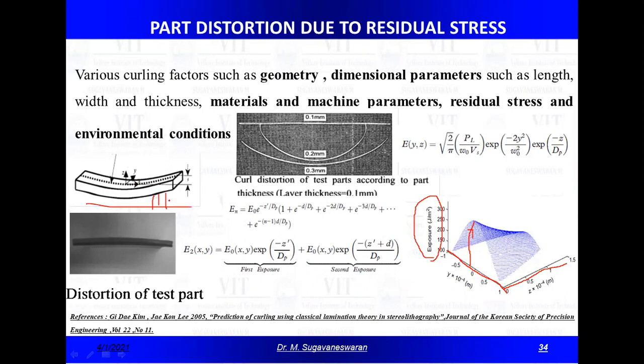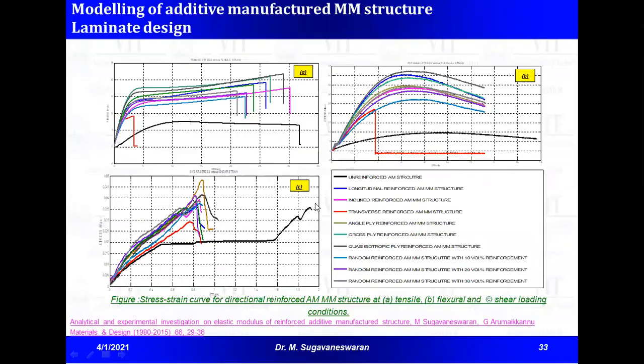But once we remove the support, especially in plastic material, that too in thin features, it automatically tends to curl, it tends to bend. So researchers have worked on this heterogeneous behavior, and it was reported that from layer to layer, the elastic modulus varies. And because of this change in elastic modulus, the material will curl, especially in thin sections. So what we have done is, according to the response we get from different orientations, we have